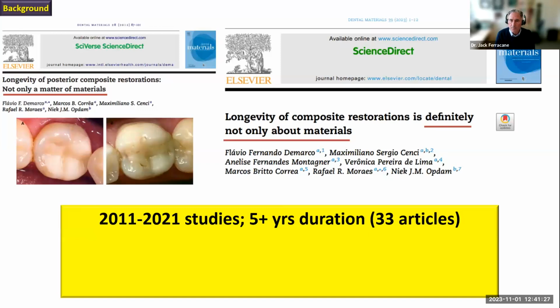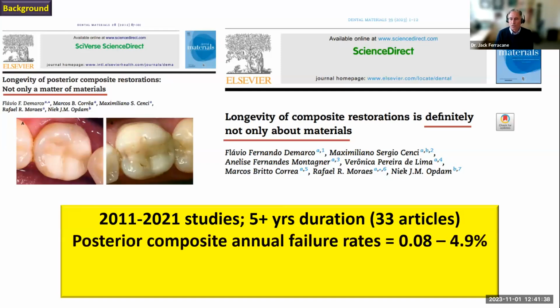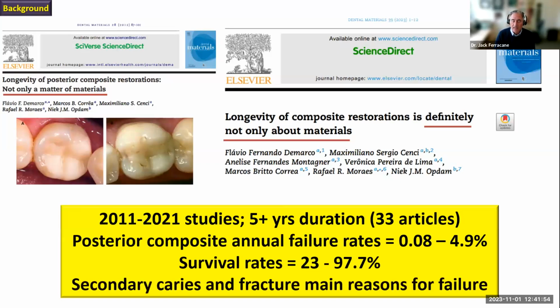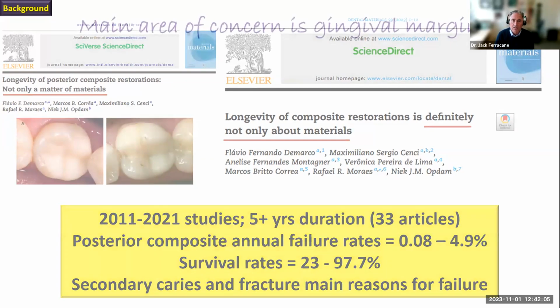So sort of in summary, the second article reported about studies from 2011 to 2021, over a 10-year time period. The studies had to be 5+ years in duration, and there were 33 articles they looked at. And what's rather interesting is that the annual failure rates for posterior composites ranged anywhere from less than 0.1% to almost 5% in these studies, with survival rates being anywhere from 23 to almost 98%. And again, they found secondary caries and fracture being the main reasons for failure. But you see this wide difference in terms of survival of restorations based upon a number of different factors.